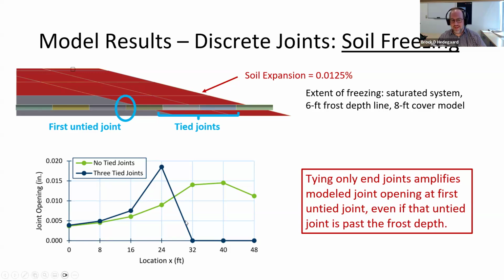So it turns out tying some of the pipe, or providing some pipe ties, actually gives you larger joint separations than if you just had left them all untied. So this actually lends some credence to the results that we saw in the database, where we saw partially tied pipes were more likely to have joint separation. And from these results, we can see that that may very well be the case, because now we're taking what would be maybe a small amount of separation in four different joints and concentrating it all into the first untied joint, just past that frost depth.